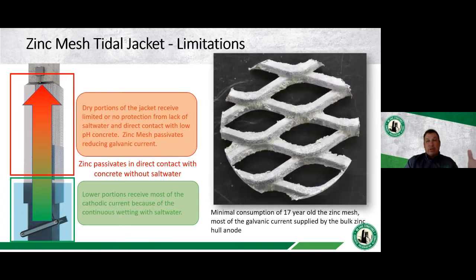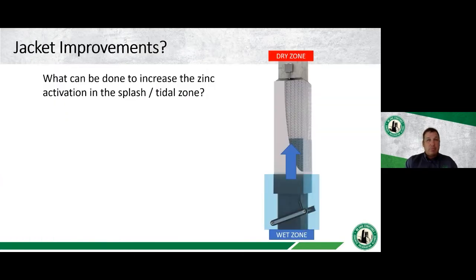And there's been a number of different field trials, and as you move farther up on the jacket systems, higher up away from the splash zone, basically the zinc is producing smaller and smaller amounts of galvanic current. This is just an example of some of the zinc mesh that was removed, and you can see that there was a little bit of corrosion that had taken place, but over a 17-year time, not a lot of the zinc had been consumed. So a lot of the galvanic current's coming off of the bulk anode and even in the lower portions of that jacket, just in that tidal zone.